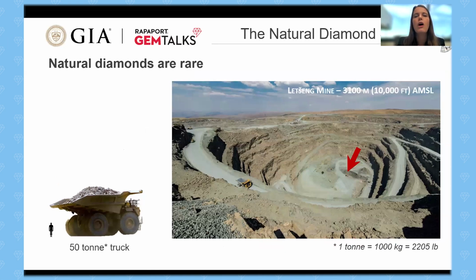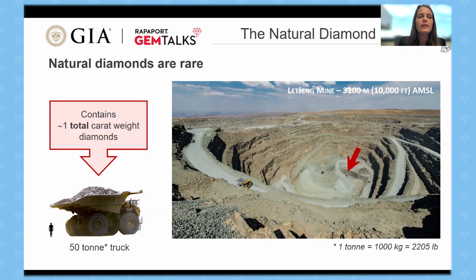So natural diamonds are rare. Here we have an example of the Letseng mine in Lesotho, where it has a very, very low grade, only about 0.01 carats per ton. So if you have this human standing next to a 50-ton truck for scale, this particular truck might only contain 1 total carat of diamonds. So you need to extract quite a lot of material indeed in order to be able to find diamonds.